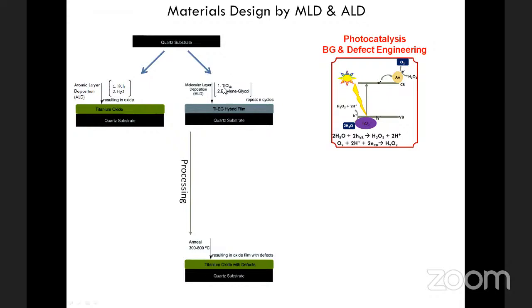We decided not to use titanium tetrachloride and water, but rather use titanium tetrachloride and ethylene glycol. Therefore, this would be molecular layer deposition, where we deposit in a layer-by-layer fashion titanium ethylene glycol titanicone films. And this results in titanium ethylene glycol hybrid film, which is amorphous. It is a combination of oxide and organic components. And then apply in the middle some processing, I will show you soon, anneal the film and get the oxide.